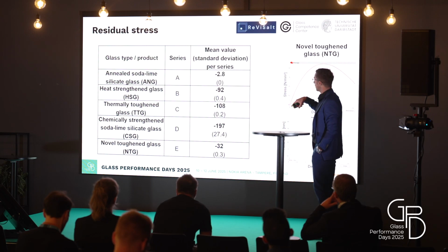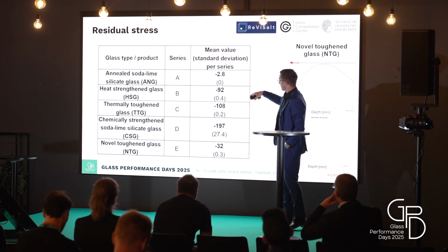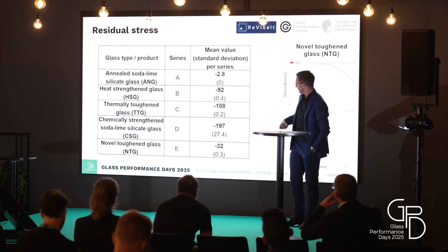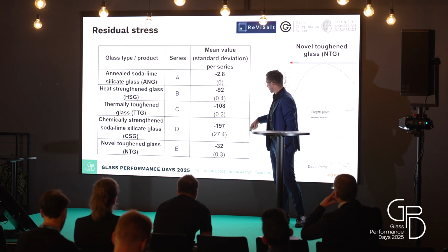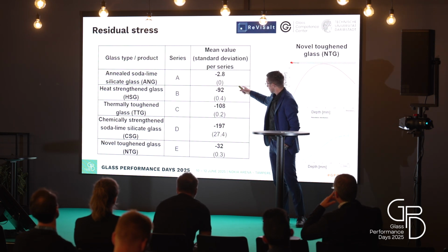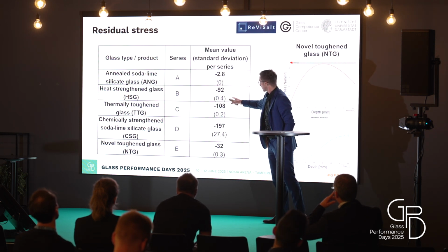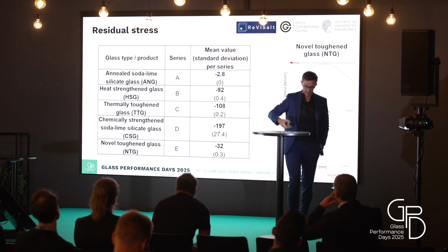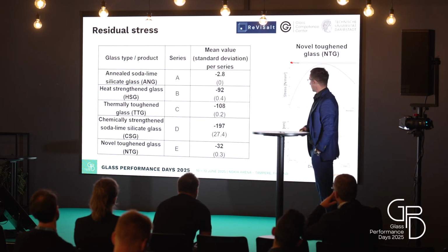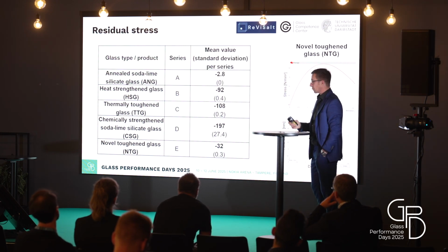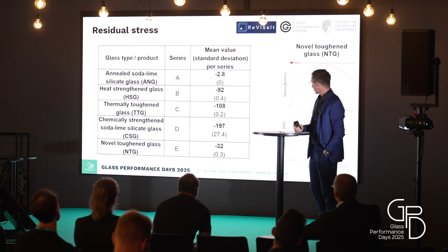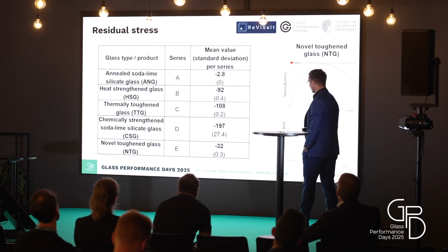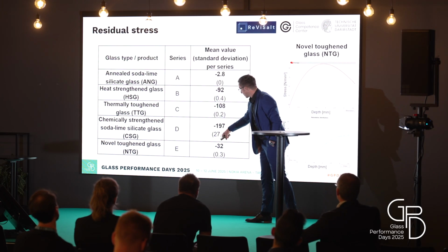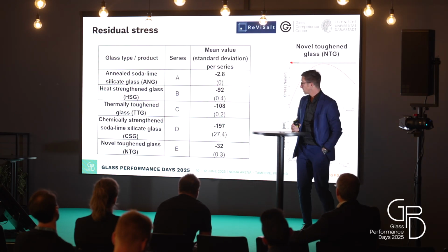Here you can see the mean value in megapascal of the series in the stress measurements. We had 3 samples, 3 different measurements, and these are more or less the typical values. The heat strengthened glass, it's a little bit too much. Here for the chemical strengthened glass part, we are in the range of 200 megapascal, and here for the novel toughened glass, we are in a range of 30.